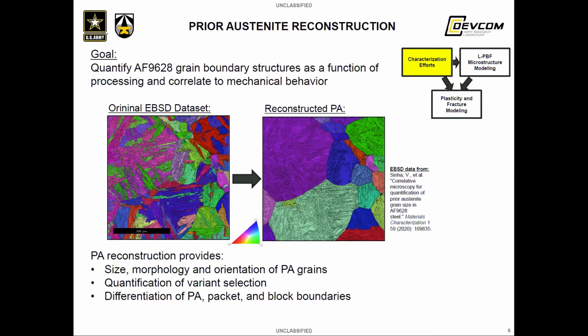As a result of the nature of the martensite transformation, there's actually a discrete number of martensite orientations that typically form when a single austenite grain transforms. These possible orientations are referred to as variants. As many as 24 of them can form from a single austenite grain, but not all 24 of them will necessarily form. The preferred formation of a subset of those 24 variants is called variant selection. And understanding variant selection is important because it has an important effect on the texture of the final martensite microstructure.